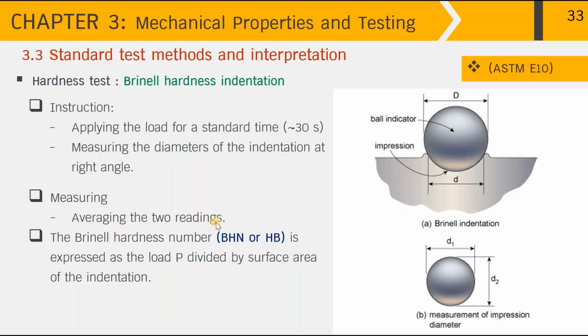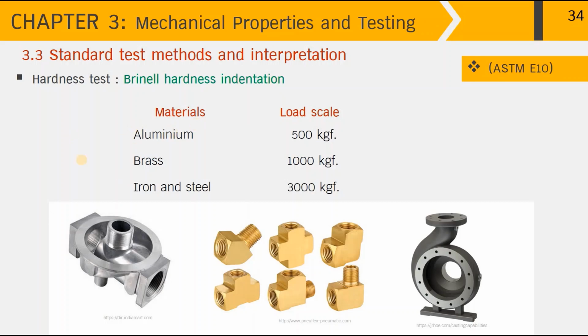After averaging the 2 readings of D1 and D2, we have the Brinell hardness number in the unit of BHN or HB, expressed as the load divided by the surface area of the indentation. Normally we can read it from the hardness chart. This slide shows an example of 3 materials: aluminum, brass, and iron and steel. These 3 materials have different levels of hardness, therefore we apply different load scales. For aluminum, we apply 500 kg force, for brass 1000 kg force, and for iron and steel 3000 kg force.